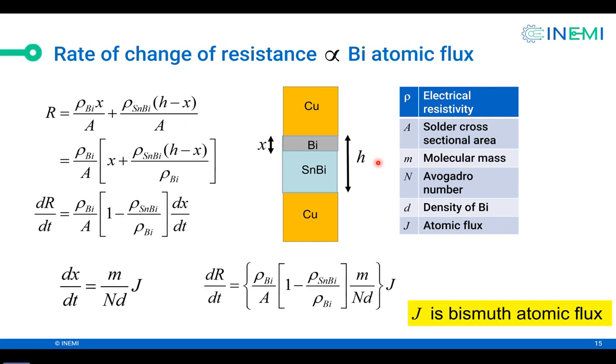Okay, one other thing I want to show before we proceed is we measure electromigration by the rate of change of resistance. So it turns out that the rate of change of resistance is proportional to bismuth atomic flux. And I won't go through the calculation, but basically we have solder between copper lines. And when we have electromigration, bismuth segregates at the anode and increases the resistance. So in these calculations, at the very end, I'm showing the rate of change of resistance is proportional to the bismuth atomic flux. And this is basically a constant.